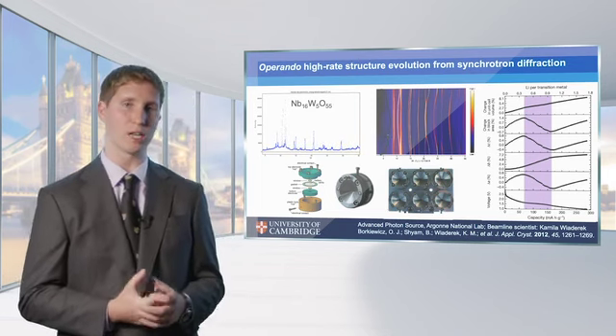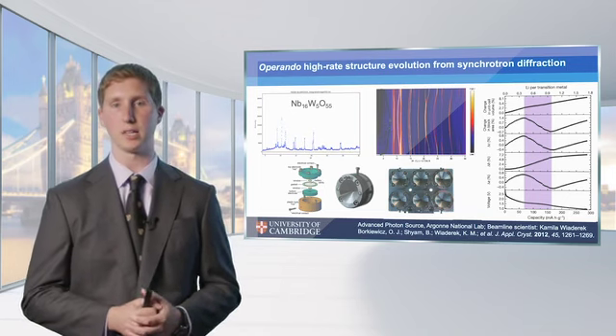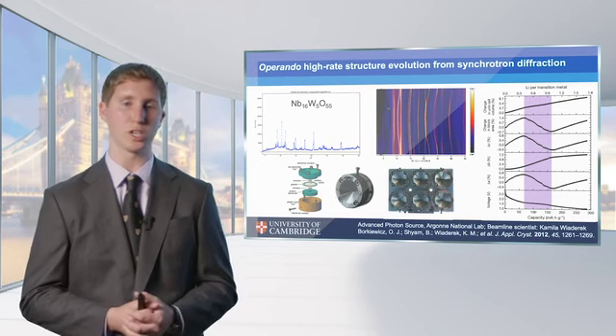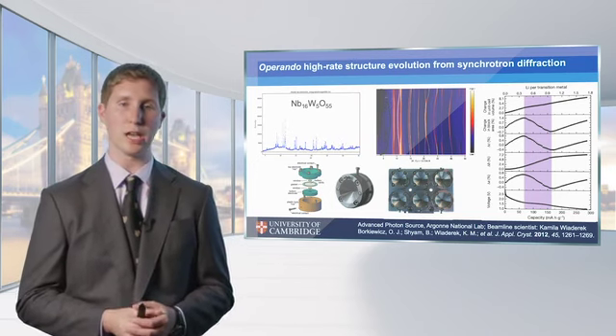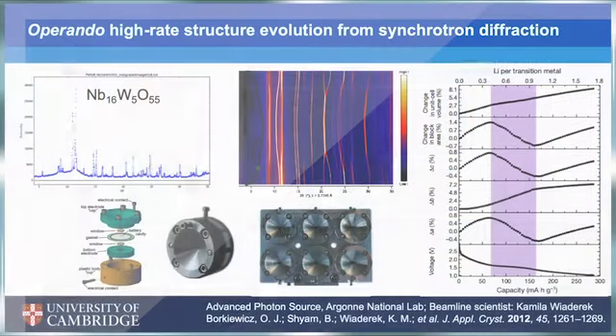And once we understood this local structure picture of how our individual octahedra were being affected by lithiation and what was being reduced, where our oxidation chemistry was coming from, we were also interested in how the overall lattice was responding. And so we did some operando high rate diffraction at the Advanced Photon Source at Argonne National Lab near Chicago. And this was work with beamline scientist and chemist Kamila Wiaderek. And so what we did was we used the Ampix cells that they developed, which is an invention of the Advanced Photon Source, in order to perform high-rate electrochemistry in the presence of an X-ray beam and get the same observable electrochemistry as you get in the conventional coin cells that we test in our lab.